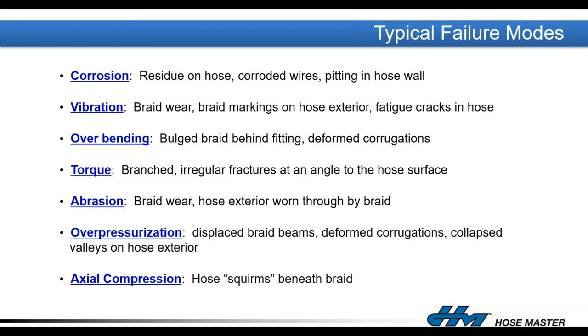So we know how metal hoses work by allowing those corrugations to move freely, minimizing the amount of stress when forming those corrugations so they have more fatigue life in service. This is now how metal hoses fail, either due to corrosive attack internally or externally because it was exposed to corrosive media that wasn't designed to resist. Excessive vibration can cause that braid to wear down into the hose. There are certain fabrication options we can provide to eliminate that problem.